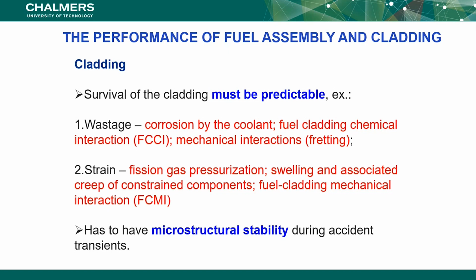Then we have strain. What is the strain? It is the fission gas pressurization. As I showed you before, you can have gas release due to the fuel irradiation. Then you have the swelling associated creep of the constrained components. So, of course, if there is too much overpressure and you also have this heated surface of the fuel, then you have a material which is a bit more elastic and it's easier to modify. And then you will get a bit of swelling. Of course, if you have some defects which are coming from the design, or they're simply coming from the production most of the time, then the swelling can find such a spot, and then you can form a little bubble, basically.